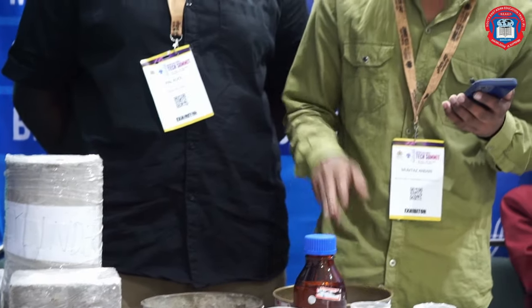But the problem is once we cast, there will be cracks. Before that, we had two tests: one is the slump test and one is the compression test. In the slump test, we check for workability before it settles down. In our test, we got 8% more workability compared to GPC and OPC. And in the compressive strength test, we got 34% more strength than normal cement concrete.